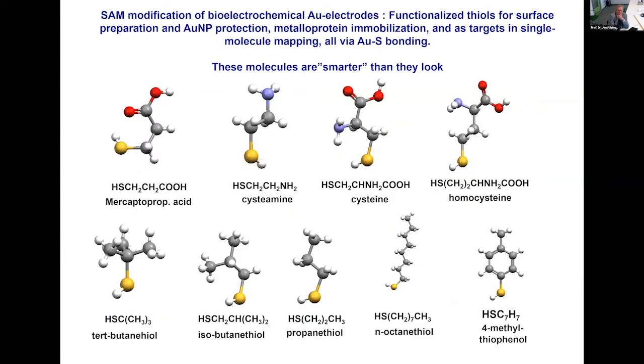We can also modify the electrodes, as we just heard. Functionalized alkanethiols are very commonly used. They are easily prepared, and they bind to the gold surface via the sulfur atom. And then they have different functional groups at the other end of the molecule. That is extremely versatile. They can be positively charged or negatively charged, neutral, large, small, and they are ideal building blocks for gentle immobilization of proteins, so the proteins can feel comfortable on surfaces such as these ones. They're also key targets in the way of studying how molecules are actually bound to the surface.